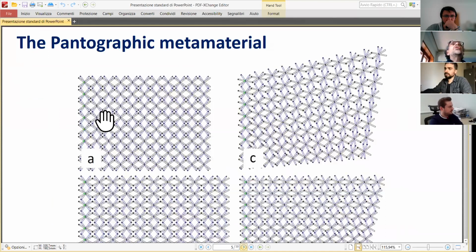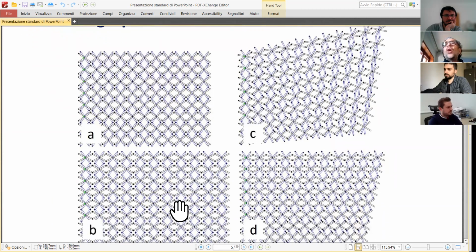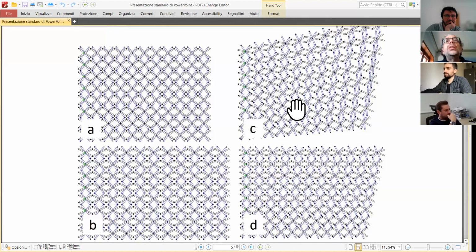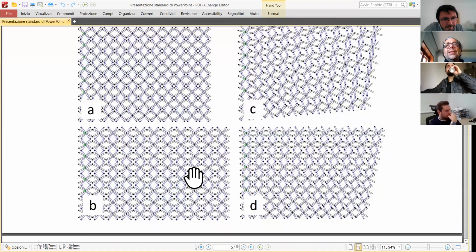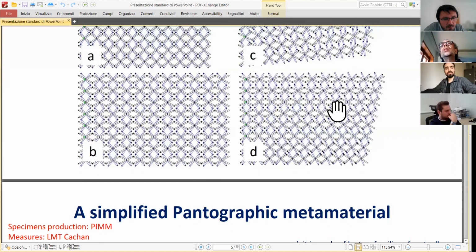So I could also invent a material like this one, which is made of two families of orthogonal pantographic beams, and these deformations which you see here are all with zero energy if the pivots are perfect. So you have a material which deforms in a homogeneous way in the plane without any deformation energy, which is what we want, because when you introduce a very small deformation energy related to the angle change in a pantograph, then you get a material which I can call a bipantographic sheet.